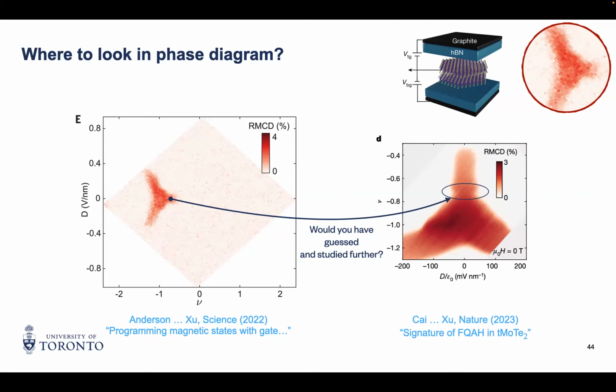So if you look at the position of that kink as a function of magnetic field and density, you see it follows a straight line. And that is a sign that it behaves more or less as a fractional quantum Hall state. That's also what you expect for a fractional quantum Hall state. You change the magnetic field, and the density of electrons needs to track the value of the B field with a specific slope, and that slope was giving you the filling.